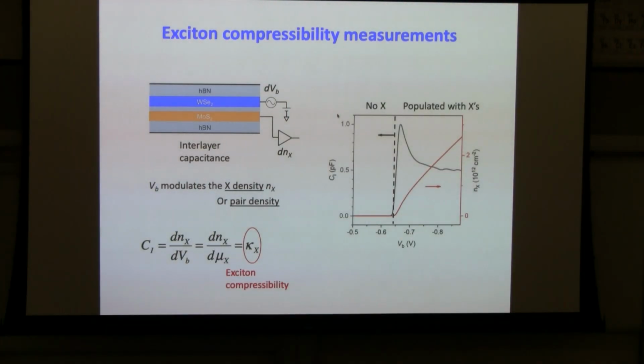So this shows an example. This is the interlayer capacitance as a function of the exciton chemical potential, or VB. On the left-hand side, there's no exciton, so the CI is 0. And once you populate excitons, you get a finite signal in the interlayer capacitance here. And if you integrate this curve, that will give you the red curve, which would tell you the exciton density as a function of the exciton chemical potential. And that's just the exciton thermodynamic equation of state.